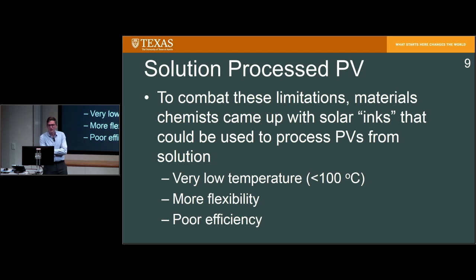And so solution process PV came about to combat some of the limitations associated with these traditional thin film technologies. The idea was that material chemists would come up with solar inks. You could make your absorbing layer, instead of doing a direct deposition on a substrate, somewhere else in a solution or as a powder or something like that, and then deposit it from a solution process and therefore expose your substrate to very low temperatures, less than 100 degrees C in most cases.